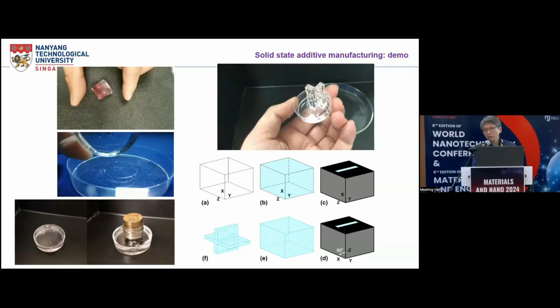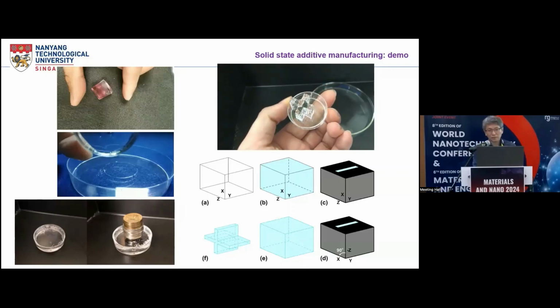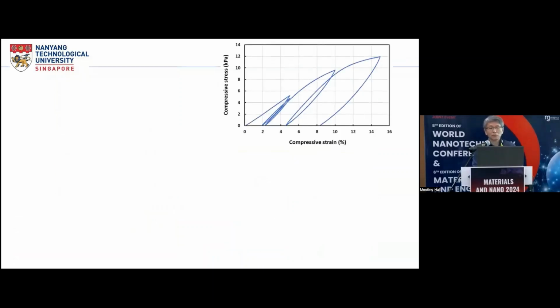And of course, there are lots of limitations because, for example, this is hydrogel, so it's quite soft. Now, let's take a look at the mechanical response of this thermal gel. This is a stress versus strain relationship of this material in compression, cyclic loading. And because it's viscoelastic, you can see it doesn't actually fully recover its original shape. But this actually is the nature of the viscoelastic material. A while later, it's able to recover fully.